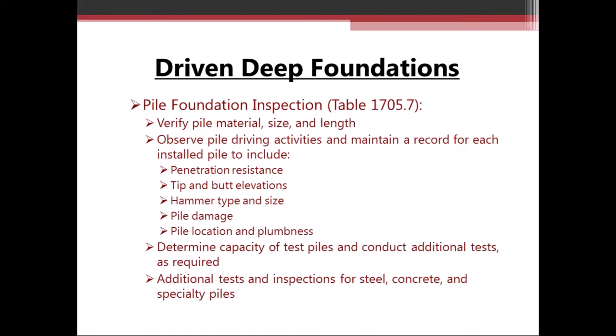They're going to determine the capacity of piles based on either static or dynamic load tests. Typically for driven piles, dynamic load tests are specified because they're quicker and cheaper, as well as any additional tests. So for steel piles, if those piles require a splice, there's going to be some weld inspection involved with that. With concrete, with driven pipe piles, oftentimes those pipe piles are filled with concrete. So there'll be some additional inspection and testing involved with the concrete placement in those piles.